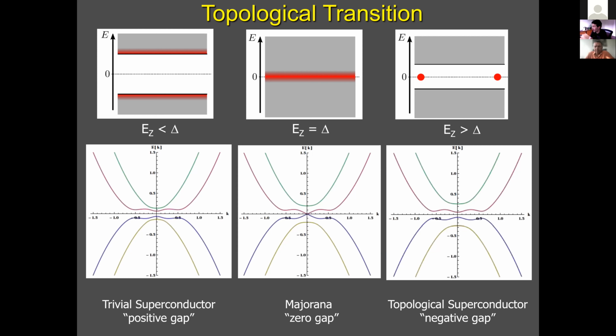Triplet superconductivity is peculiar. One of the practical properties is that it is sensitive to disorder much more. So in spin singlet superconductors, we have this thing known as the Anderson theorem. And Anderson theorem tells us that scattering on non-magnetic impurities does not hurt superconductivity. So the gap remains the same, coherence length remains the same. So that means that we can have a pretty disordered material, like an alloy, niobium titanium, a completely disordered material, and superconductivity can be very strong. And there is no such theorem for P-wave for triplet superconductors. Any disorder, magnetic or non-magnetic, destroys this superconductivity. That's why we also need extremely clean interfaces and crystals to see it.